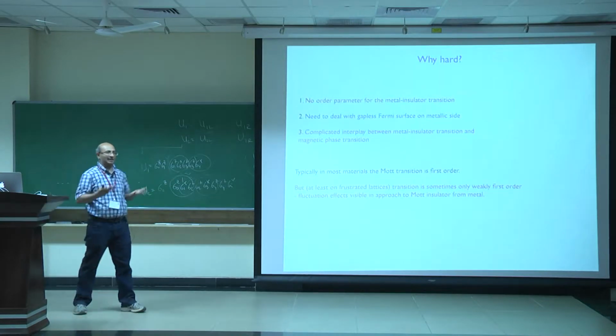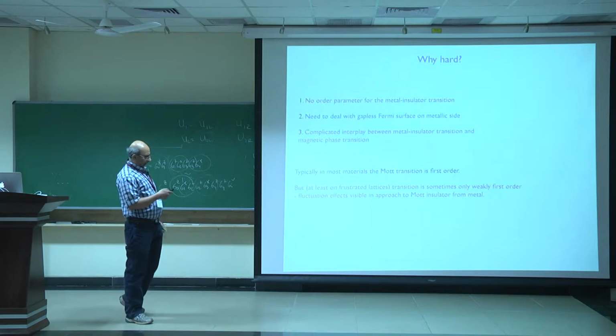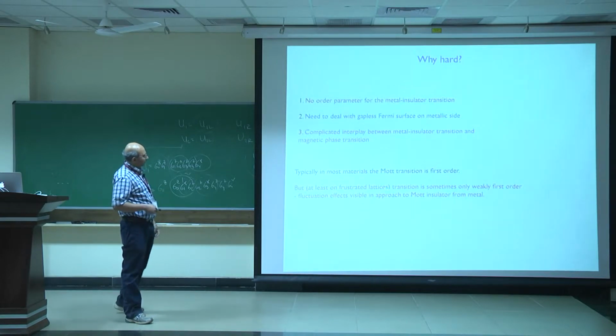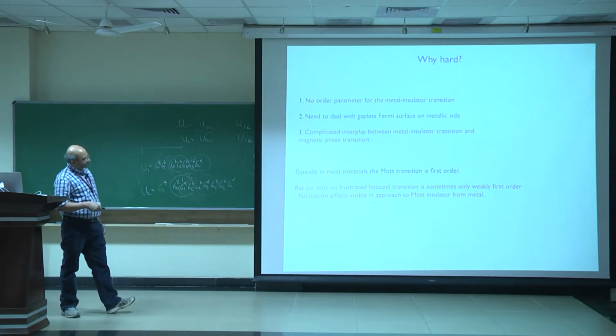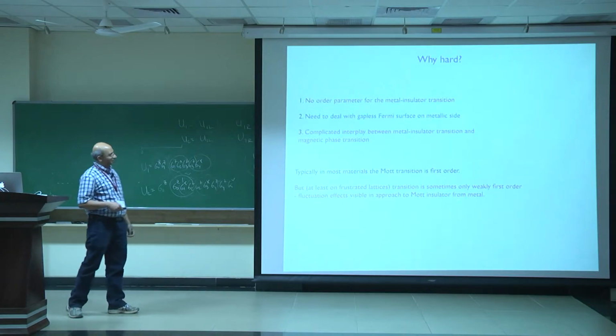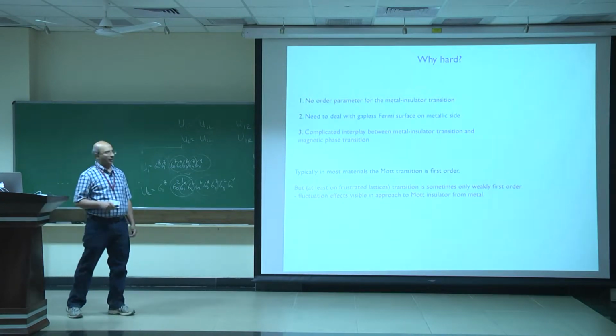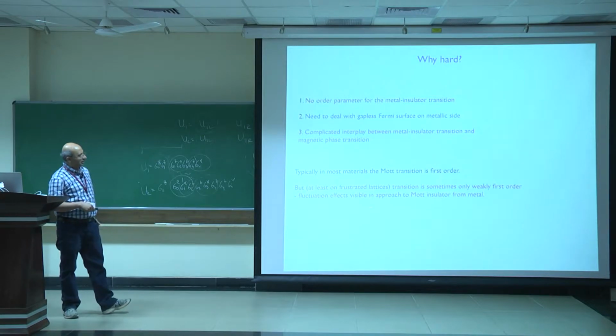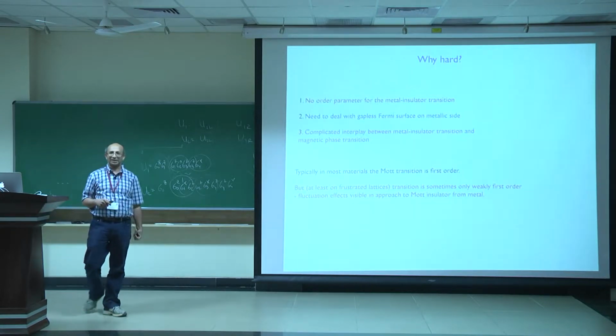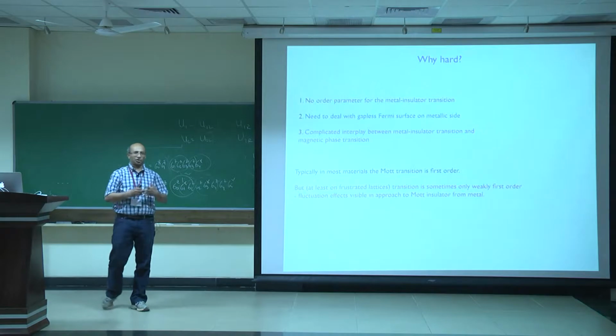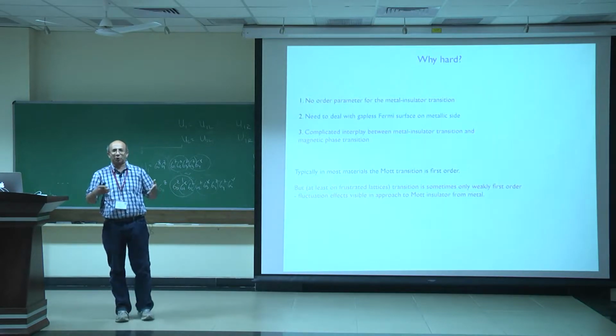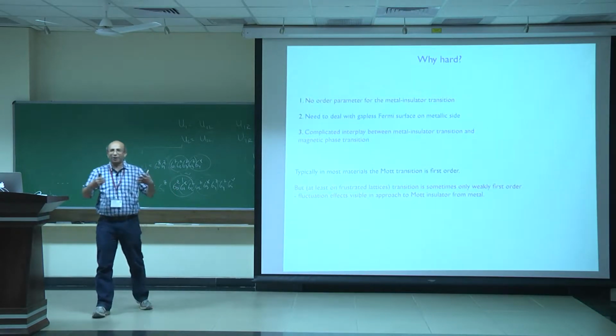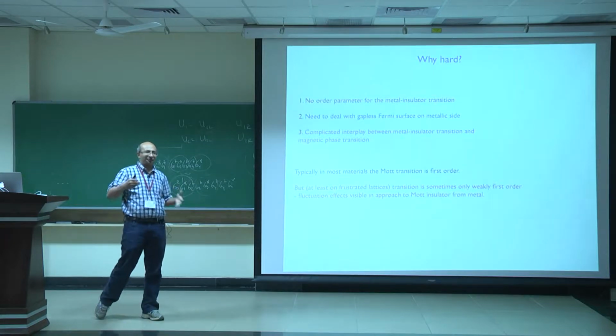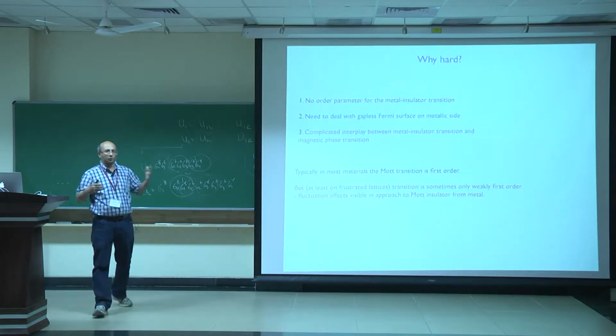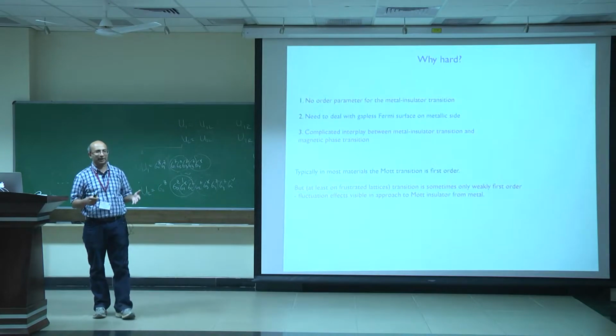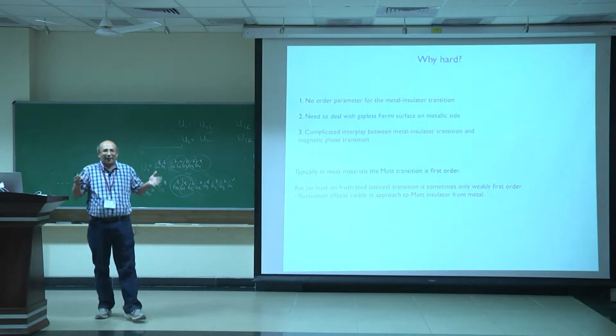Other than that, it's first order. But despite it being first order, in at least some frustrated lattices, the transition is only weakly first order, and you do see fluctuation effects that are visible as you approach the Mott insulator from the metal. So it's not just a strong first order transition, it's weak first order, so it looks like it may try to be a second order transition, and you see various phenomena that you attribute to the impending Mott localization, but it's not quite a second order transition.